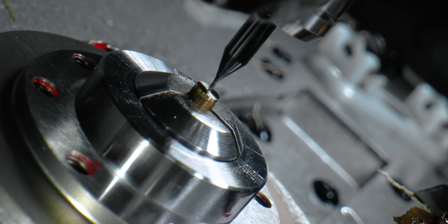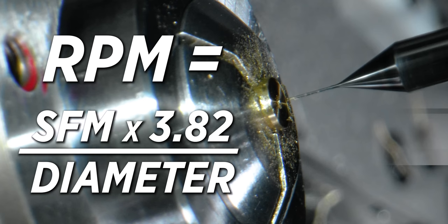So let's focus first on the RPMs. Your RPM is going to be based off something called your surface footage and your surface footage is going to be based off of what type of material you're running. Now we're cutting heat treated stainless steel and Mikron Tool who gave us these drills told us to run these drills at 60 surface footage.